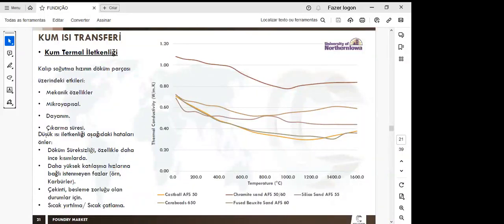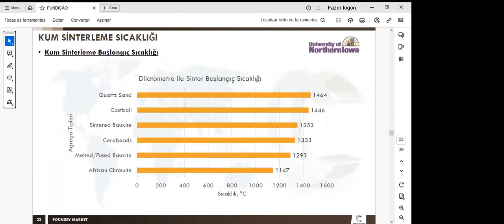With this characteristic, the low thermal conductivity, we can solve some problems. The kinds of problems that we can solve are misruns, cold shuts, especially in thinner sections; unwanted phases related to high solidification rates; shrinkage in situations where there are difficulties to feed; and hot tears and hot cracking. These are types of defects that we can solve with types of sand like Castball. When we use a chromite sand, we can solve other types of defects, but normally we start to have problems when we use chromite.